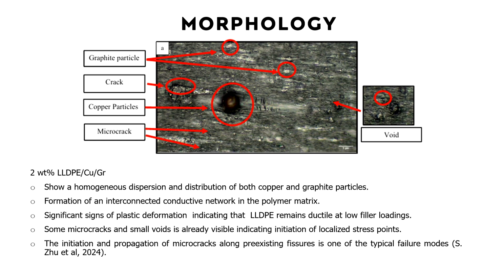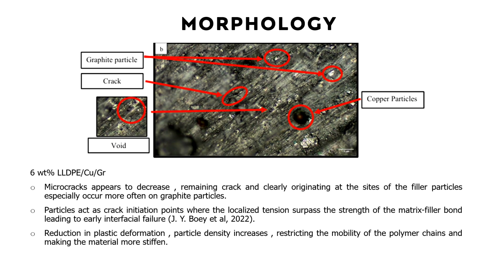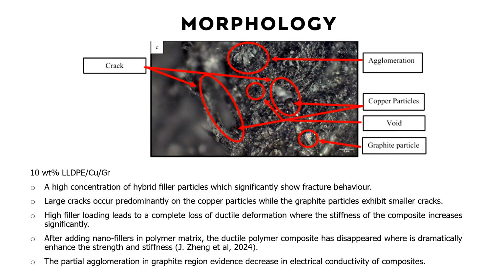If we look at the morphology, we can obviously see the copper particles and the graphite particles dispersed within the LLDPE matrix, and this is for 2 weight percent. This is for 6 weight percent, where we can see that the number of dispersed copper and graphite particles increases, and also for 10%, there are numbers of copper particles and graphite particles present within the matrix of LLDPE.